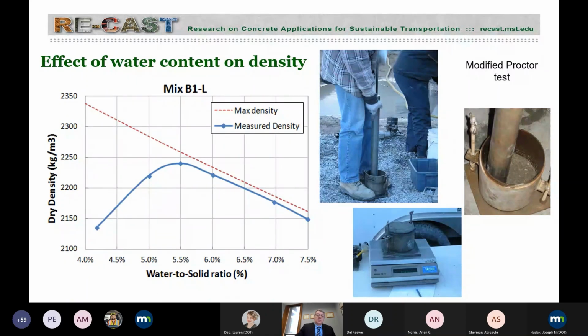As you know, in the mixture design of RCC, we try to optimize the water content, the water-cement ratio. In this case, it's shown as a water-to-solid ratio versus the density. That density is determined using the modified Proctor test. And you see that the in situ density increases as you add more water. It makes it easier to consolidate, and you reach a peak, and beyond that, you're just adding porosity to the mix, and the weight is reduced. So 5.5% in this case is an optimum water content.